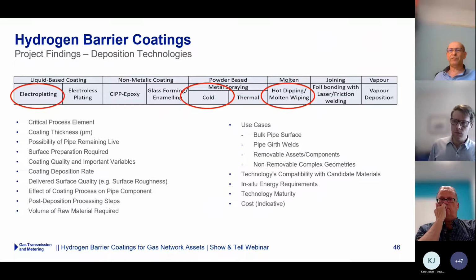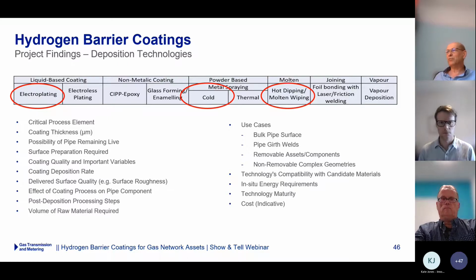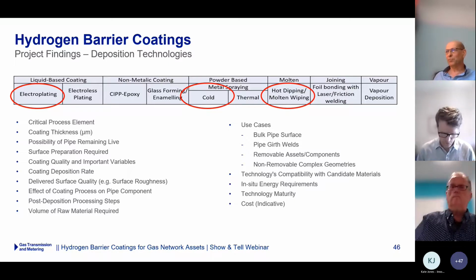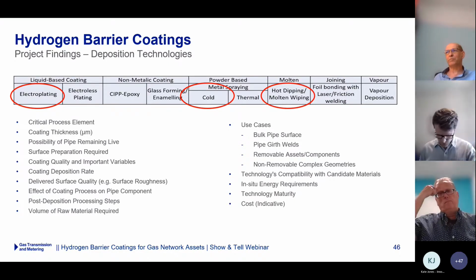With this subset of metals in mind, we explored the potential deposition techniques that we could actually apply to National Grid gas network assets. We considered a wide range of aspects, including the coating thickness that we need to achieve, the volume of material that you need to be able to do that, any waste products, the quality of the coating, preparation and post-processing steps, and any significant process conditions that would be really difficult to achieve, like a high vacuum, for instance, that would be complete showstoppers to apply into the network.